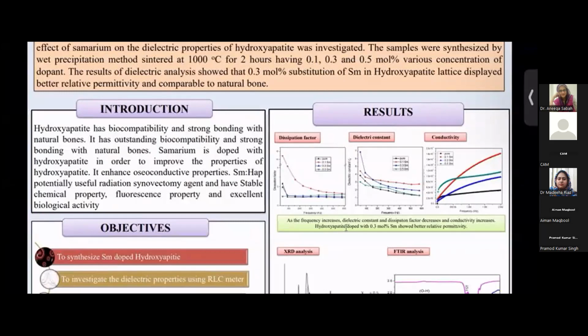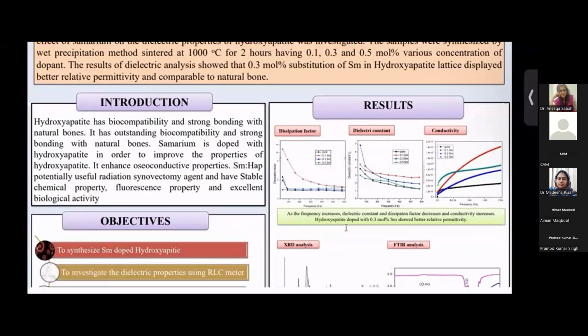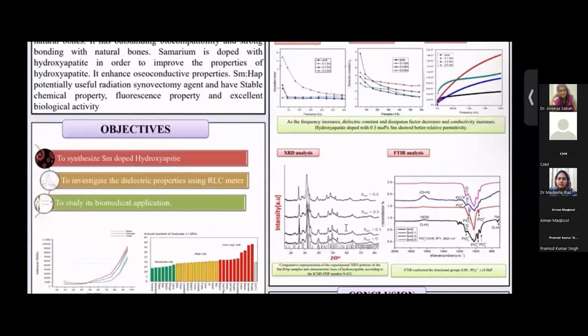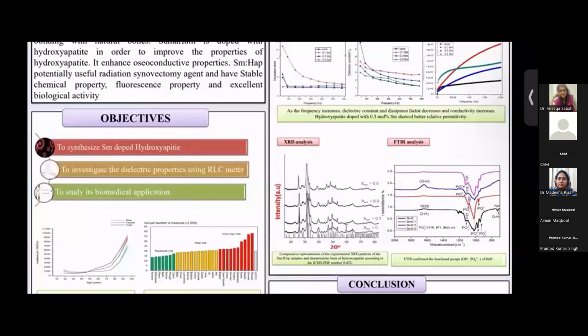Now, XRD analysis. Samples of samarium-doped hydroxyapatite exhibit the characteristics of pure apatite with good crystal structure. These results demonstrated that samarium ions have successfully substituted without affecting the crystal structure. FTIR analysis. The FTIR spectrum shows stretching modes of the hydroxyl group and phosphate group at 724 and 1123 per centimeter wave numbers.